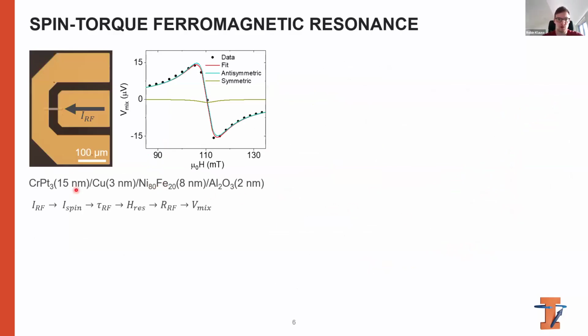So then we moved on to spin torque measurements, and we used spin torque ferromagnetic resonance for this. We patterned chromium platinum 3, copper, and permalloy, where the permalloy acts as the ferromagnetic layer. The copper is a spacer to magnetically decouple the chromium platinum 3 from the ferromagnet, and then the chromium platinum 3 is the spin source.